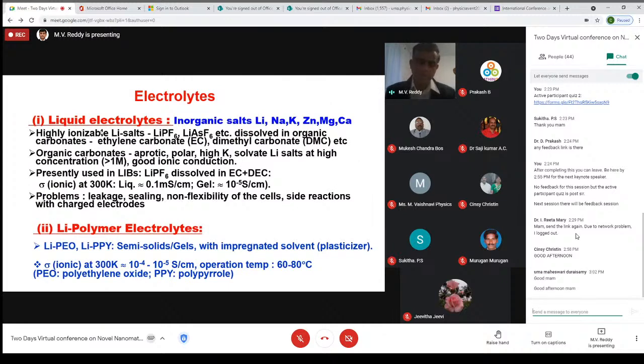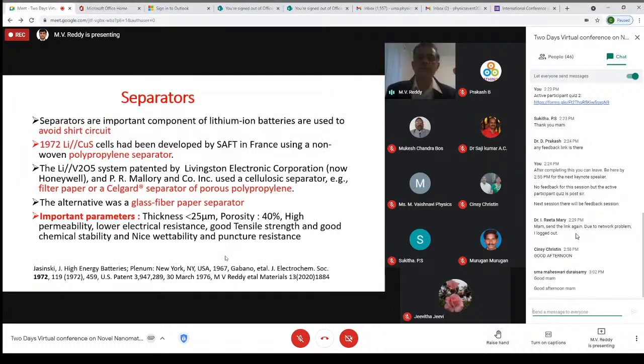Suppose you talk about inorganic salts, lithium, sodium, and so on. For sodium or any type of battery, the respective salts are needed. It's very important to use organic solvent. The reason is that if you use an organic carbonate solvent, we can go to slightly higher voltage. If you use an aqueous system, the maximum we can go is 1.23 V because of the decomposition of water. So these are the problems, along with sealing and flammability issues. That's why people have to look for polymer electrolyte based composites. Again, here we need to consider the operating temperature, etc.